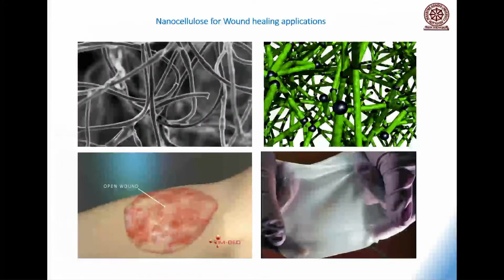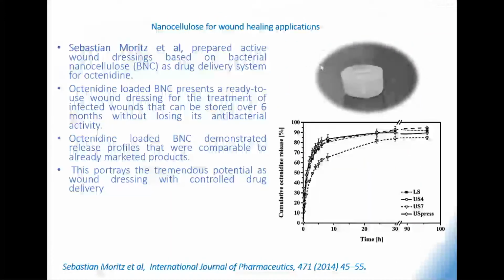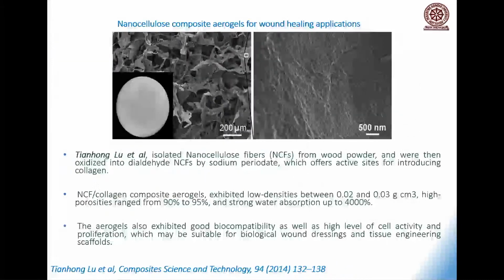Now let me show you another interesting aspect. Nanocellulose is a very good platform for sustained release of antibiotic. You see, Sebastian Moritz, he made a beautiful aerogel. This is actually bacterial nanocellulose, not nanocellulose from pineapple, because bacterial nanocellulose is the most pure form. Cellulose made from bacteria. And you can see the aerogel made by Professor Sebastian. And then he introduced antibiotic into this platform. And look at the cumulative release of antibiotic. So the message I wanted to give my young PhD students is, this is an excellent platform for sustained release of antibiotic using nanocellulose. Let me show you another interesting slide.